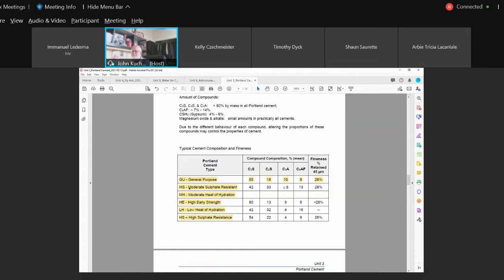What they do is use general Portland, GU, but increase the cement content. Instead of using 340, they may use 380, or 400 kilograms of cement, making a stronger concrete mix. Not because they need it for loading or capacity of cars, they just need it to get that 20 MPa quicker. They can open pavements in the City of Winnipeg if they get 20 MPa. So if it typically would take a week to get 20 MPa, now they can get it in about 3 days. They just boost up the cement content.